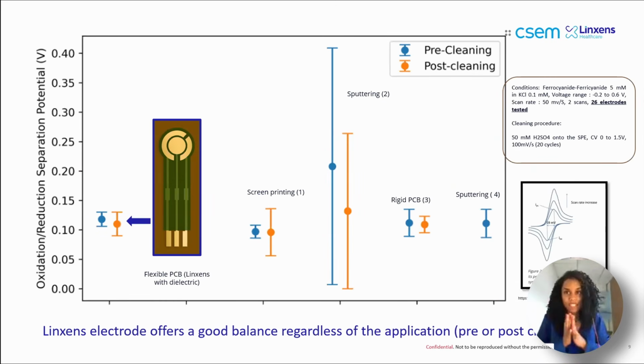So we continue this analysis, this electrode performance evaluation. We try to see if the cleaning impacts the quality of the performance of our electrodes. So we studied the oxidation-reduction peak separation potential. And just for your information, in general, a good reversible system presents an oxidation-reduction peak separation potential around 59 millivolts. In our case, with and without cleaning, we have a peak separation potential around 100 millivolts.